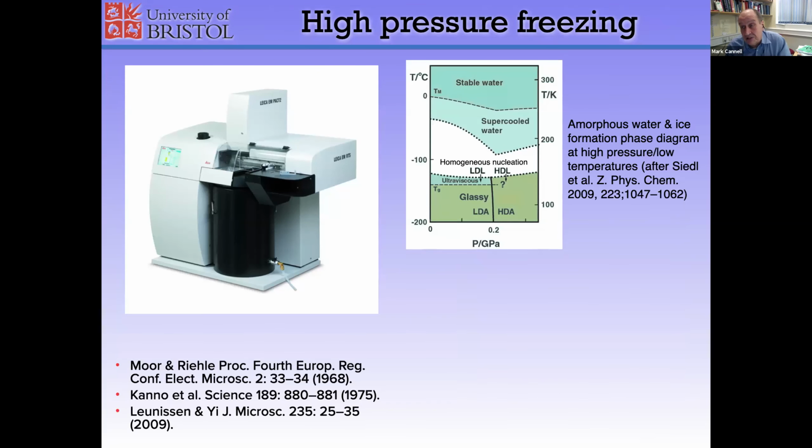Which brings me now to the subject matter that JMCC thought was interesting enough to invite me to give you this seminar. And it's about high pressure freezing, a way of doing electron microscopy in a slightly different way. The idea is to use fixation of preparation without dehydration and strong chemical fixatives such as glutaraldehyde that cross-link proteins. And we do that by trapping the tissue in amorphous ice at high pressure very, very quickly.